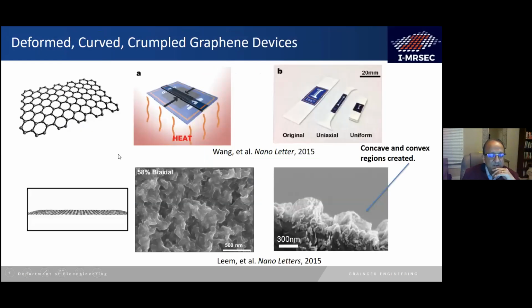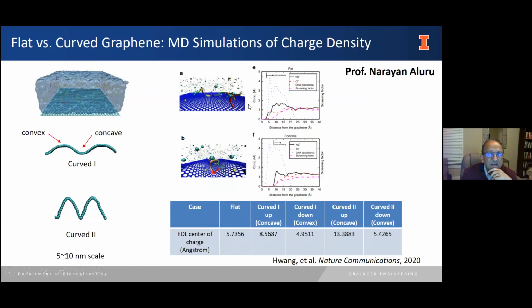So using that idea, we developed a crumpled graphene sensor. And this approach was also published before, in terms of attaching graphene to a polymer layer and then shrinking it so that the material shrinks and the film is crumpled. This is through an NSF MRSEC center that we have here. And Professor Aluru, a close collaborator of ours, we asked, can you simulate this and see what's happening?